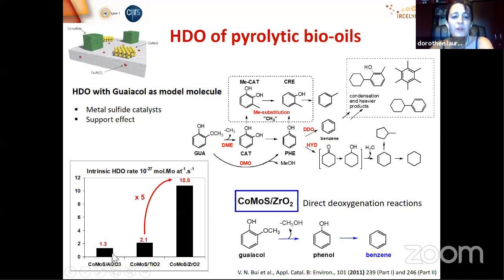And in fact, when we compared various supports for CoMoS catalyst, we observed a very high intrinsic HDO rate for the catalyst supported on zirconia compared to titania or alumina. And in fact, it is because with this catalyst, CoMoS supported on zirconia, you've got direct deoxygenation reactions, and you go directly from guaiacol to phenol and then to benzene. So it's very, very efficient, but it is realized in gas phase. So you've got only guaiacol in gas phase in contact with the solid catalyst.